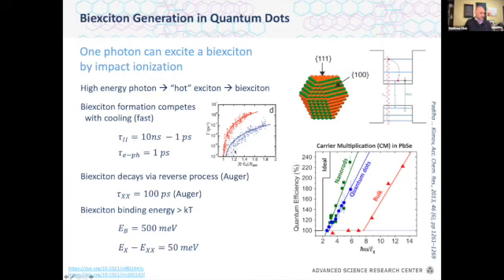I don't want to spend too much time on this, but the end result is that there are significant deviations from what you would call ideal behavior, meaning as soon as you have enough energy to create a second electron hole pair, ideal behavior would say you create that. And so on average, for every input photon, you would have 2 excitons. Real systems deviate significantly. In fact, the threshold is a little bit elevated from the thermodynamic limit. And if we think about where we finally get to the limit where we have on average 2 excitons from one photon, it's several times the band gap of the quantum dot already. All right, so that's important.